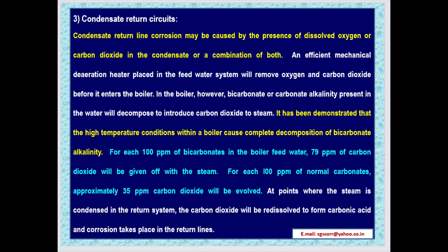In the boiler, however, bicarbonate or carbonate alkalinity present in the water will decompose to introduce carbon dioxide to the steam. It has been demonstrated that the high temperature conditions within a boiler cause complete decomposition of bicarbonate alkalinity. For each 100 ppm of bicarbonates in the boiler feed water, 79 ppm of carbon dioxide will be given off with the steam. For each 100 ppm of normal carbonates, approximately 35 ppm of carbon dioxide will be evolved.